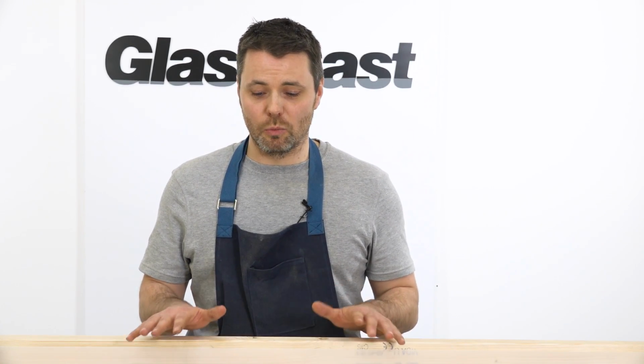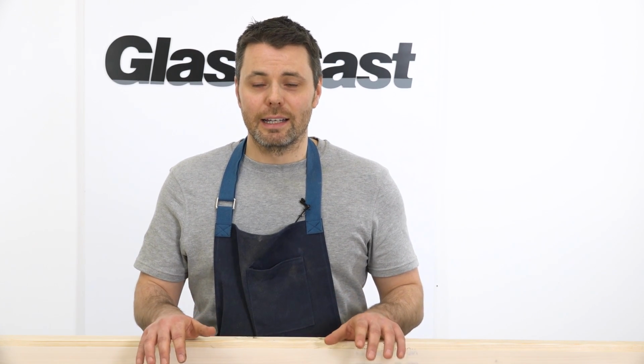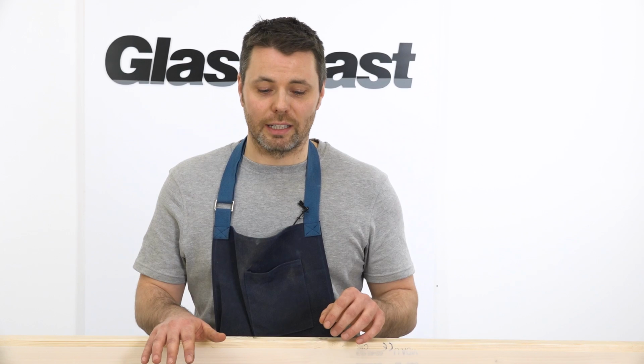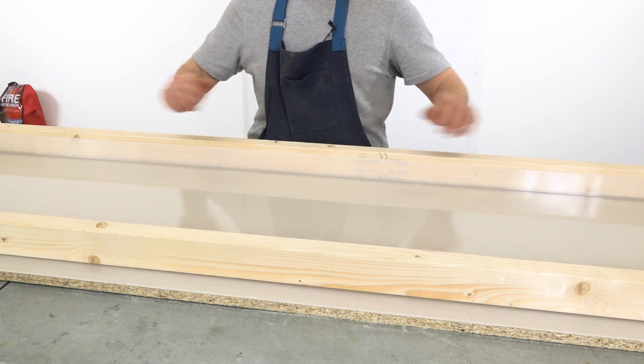So the real key to success whenever you're working with resin and wood in a project like this is to do the process in two separate stages. The first stage is to pour a very thin layer so that we can seal the underneath of the wood and any exposed areas. The second pour is your main pour to bring it up to the top level. Our recommendation for this base layer is to allow 2 millimeters over the total area inside your barriers. We've worked out that we need 1.6 kilograms, and this comes out of the total 10 kilogram requirement.